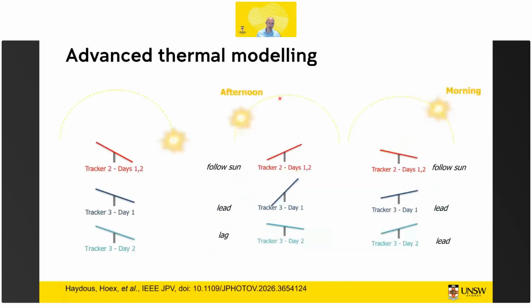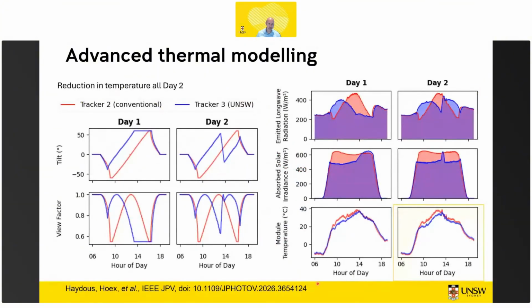And one thing we were able to do with our more advanced modeling is to look at different tracking strategies. So if we look at a tracker that is just following the sun versus a tracker strategy where, if it's curtailed, it is curtailing by pointing away from the sun. It can do it in 2 different ways. It can move quicker or move slower, so be behind in tracker angle or ahead in tracker angle. And we were then able to study what's the impact on the heat exchange and then overall the temperature.